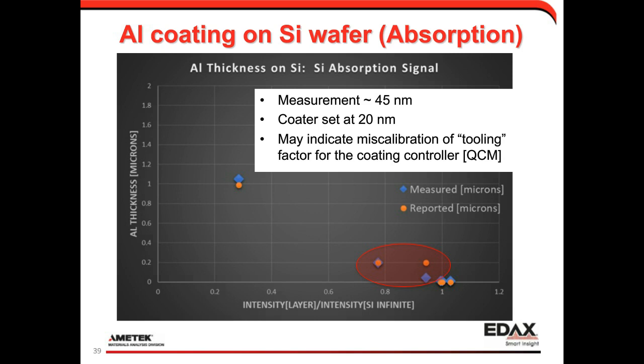Now, the way these coaters work, there's a coating monitor off to the side, a quartz crystal. The quartz crystal vibrates at a certain frequency, and as you deposit material onto the quartz crystal, the frequency decreases. So you can set these up and calibrate them for a certain set of deposition characteristics.